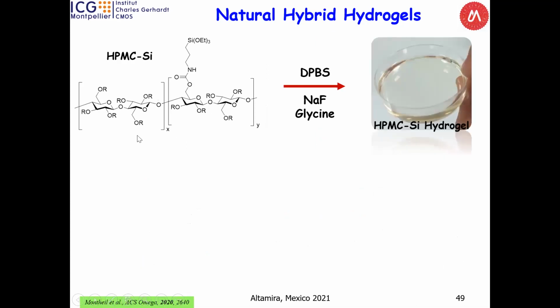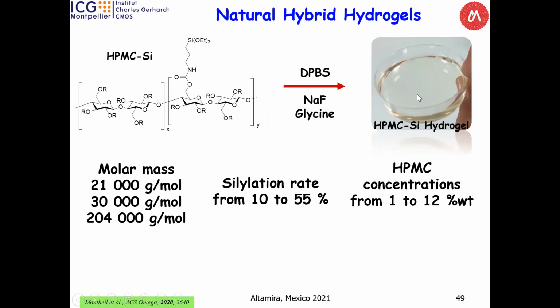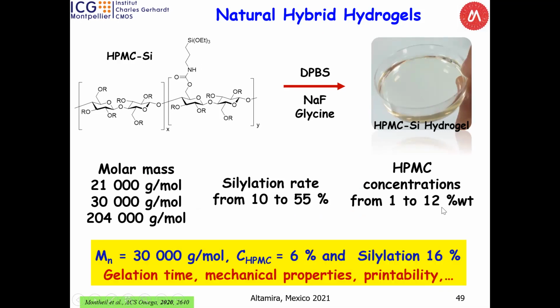So I would like to show you now the last results. We took it and we put it in PBS with a mixture of F- and glycine. We prepare the hydrogel. You can see it's a very transparent hydrogel. Stable hydrogel, with mechanical properties that can be controlled by changing the mass of your biopolymer, or the silylation rate, or the concentration from 1 to 12. It's possible to obtain that.